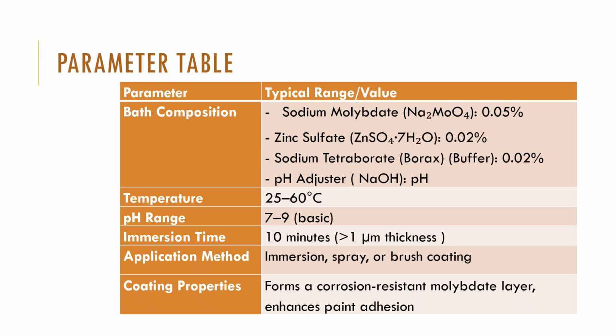So this works at a temperature of room temperature to 60 degree Celsius. So we have a pH range of 7 to 9, basic. Okay. Immersion time 10 minutes gives 1 micron thickness or slightly greater than 1 micron thickness. Okay. If you allow it to go for immersion for 10 minutes.